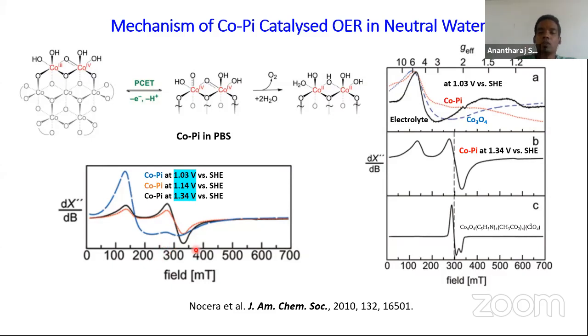0.335 Tesla, which corresponds to the G factor of 2. And when they reach the potential of 1.14, where the oxidation of cobalt occurs, and when they reach the potential of 1.34, it even increases. So you can see the growth in peak. So the amount of unpaired electrons, or cobalt 4 plus ions, that are being formed. So this is how they actually proved this mechanism.